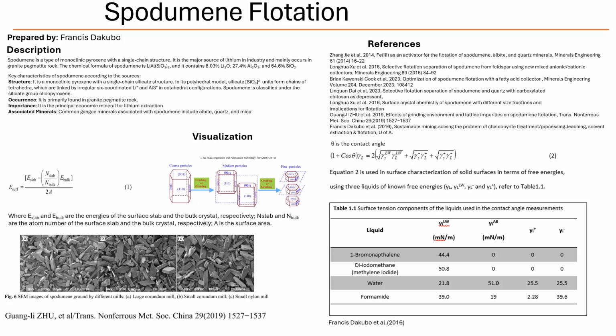That's wild. It is, and there's this fascinating experiment mentioned where they've tried acid pickling. Acid pickling. Like cleaning it. Essentially, yeah. They used acid to wash off these surface metal ions from the ground spodumene. And guess what? The flotation tanked. Totally. Really poor flotation response. Didn't matter how it was ground initially. It strongly suggests those surface metal ions are somehow crucial for the collector to attach properly. Okay, so surface contamination or maybe activation from grinding is key.